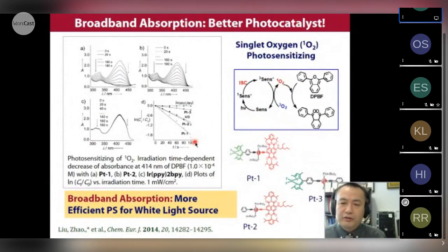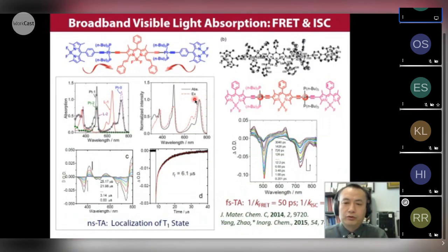We also did a simple experiment to confirm the photosensitizer with broadband absorption is actually more efficient than the photosensitizers containing only one chromophore. So this is the structure for conventional triplet photosensitizer. We have a single chromophore, but we have only one major absorption band. But for the new one, we have much broader absorption. The experiments confirmed that we can have more efficient singlet oxygen production with a white light excitation because we have broad absorption. So I think this method will be useful for photocatalysis. We prepared other metal complexes based on similar idea. So this one, we cover a large part of the visible region from 400 to more than 700 nanometer.